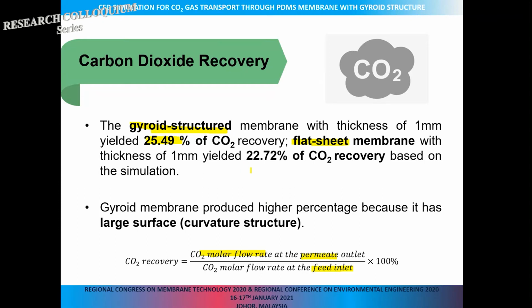But we believe that because this simulation was conducted using one unit cell of the gyro structure membrane, if we run the simulation for a larger membrane module, the CO2 recovery might be increased. So the reason here for a higher CO2 recovery for gyro structure may be because it has a larger surface with the curvature structure for the gyro membrane.